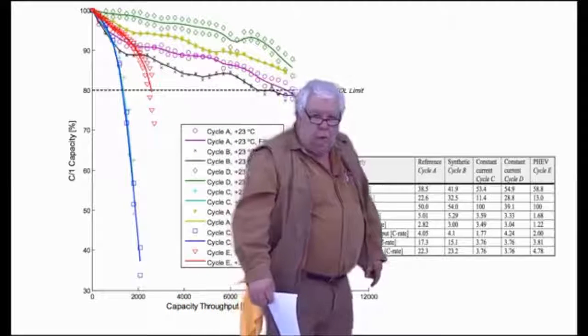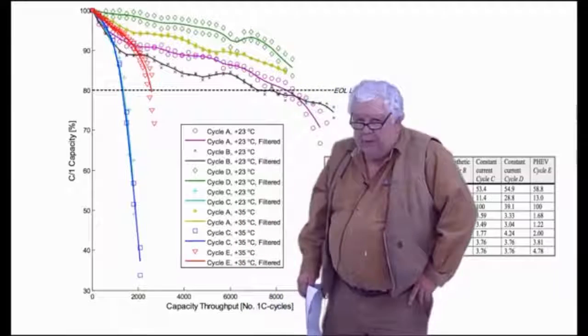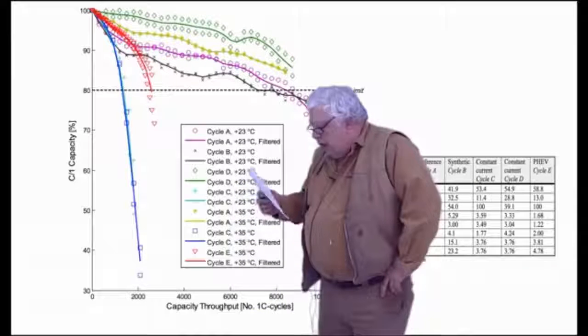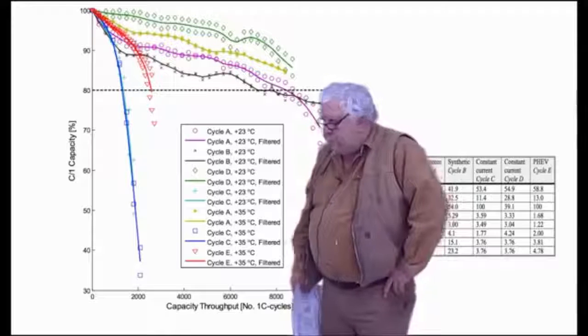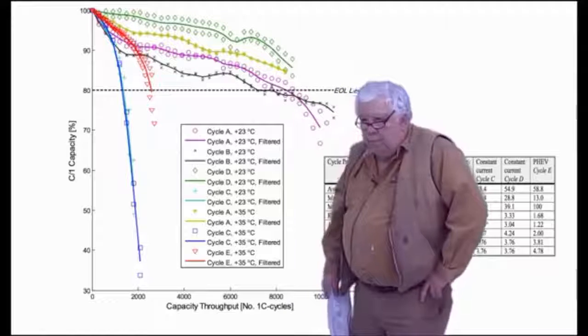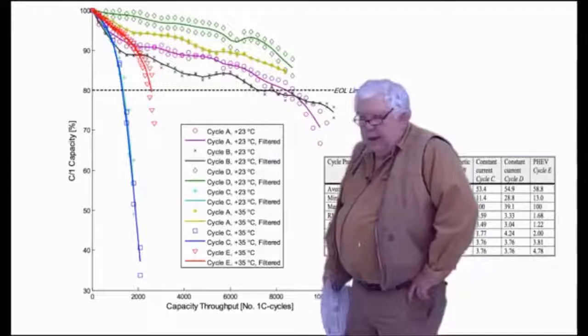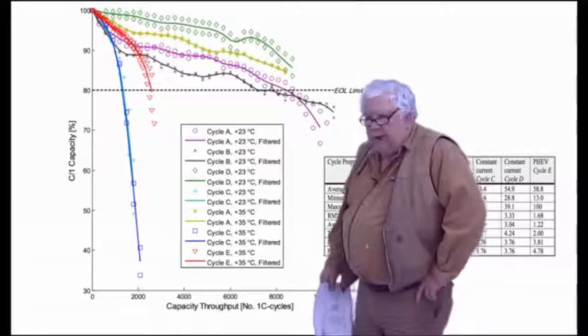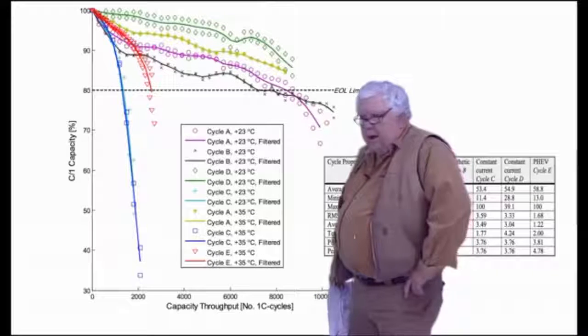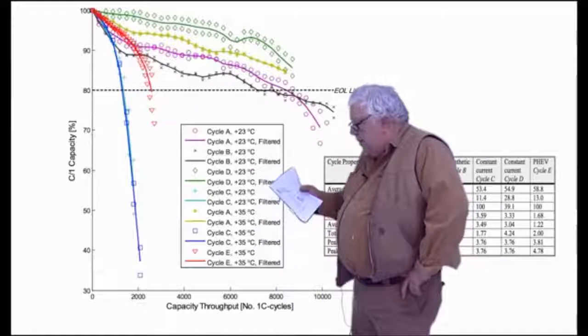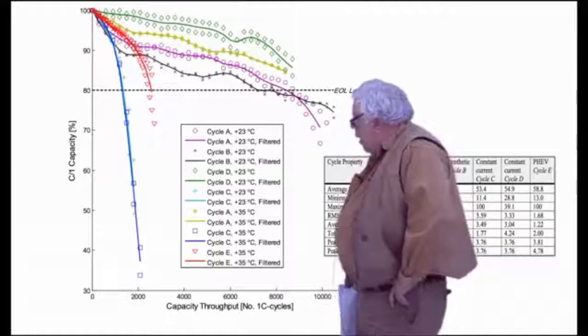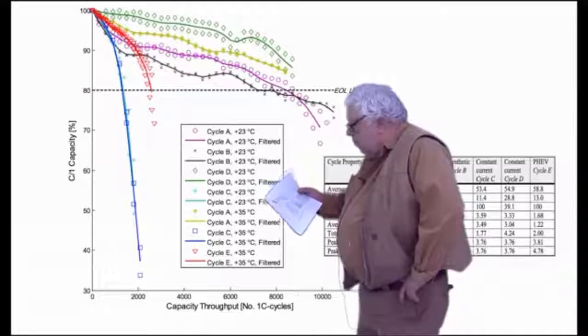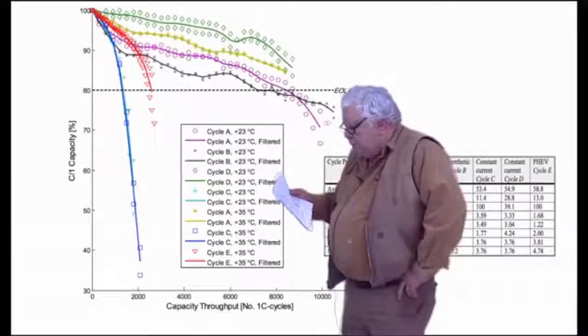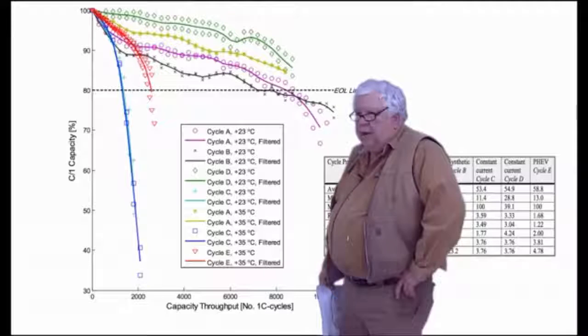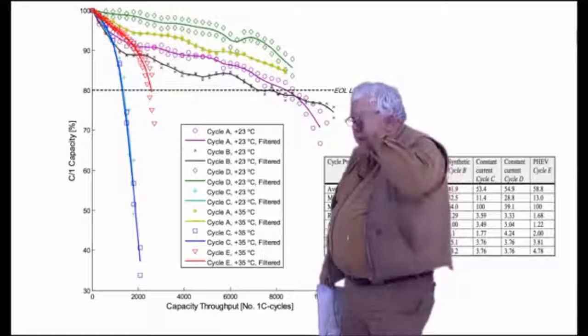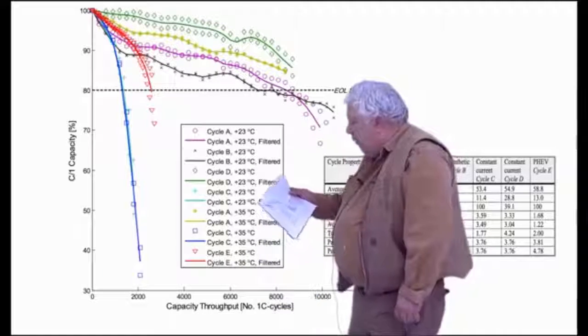He wanted to see what the effects of temperature was on life of the batteries, and stated early in his assumptions that, of course, it would cause earlier failure. Arrhenius law, our equation, and unfortunately his data supported, in my view, that for some reason these cells, everything in them works better at higher temperatures up to a point. And I think that point is about 45 degrees centigrade. Doing this at 35 degrees centigrade, what's that, a little over 100 degrees Fahrenheit, the cell lasted noticeably, demonstrably, and measurably longer than it did at 23 degrees centigrade. And normally you'll see our specs of cycle life and our curves at 25 C, but for some reason he used 23.